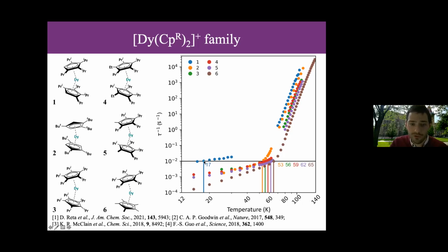And so we find that 1 has the fastest relaxation rate, so it's quite a lot faster at low temperatures than the others. And then 2 to 6 are much closer together than 1 is, but still there is some splitting of these systems. And at the higher temperature end, where we're talking about the Orbach relaxation, there is a dispersion between these systems. So 1 is always the fastest, and 6 is always the slowest. And in fact, 2 to 5 are very, very close. And if you take into account the uncertainties of relaxation rates from a distribution model of their relaxation times, actually 2 to 5 cannot be distinguished in this regime. They're actually within error the same. But 1 and 6 are distinctly different. And so the question we asked is, why are they different?